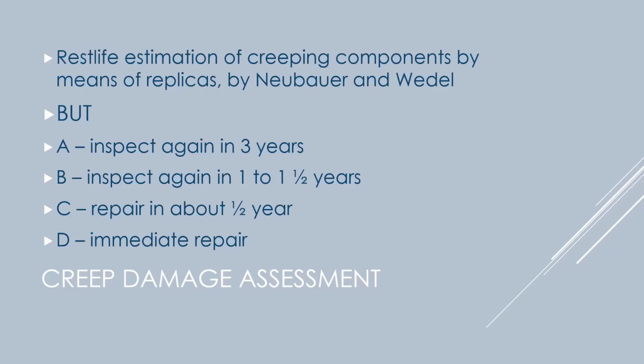So they came up with different damage categories, A, B, C, and D, and it doesn't tell you how much remaining life there is. It just tells you what you have to do for your next inspection. So if you had isolated creep voids, like A, you would inspect again in 3 years. And if they're starting to get aligned, then you'd inspect again in 1 to 1.5 years.